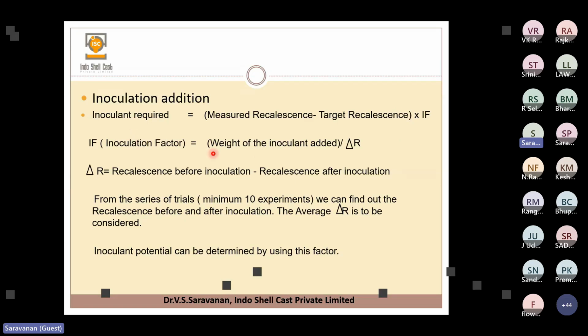So the inoculation factor is the weight of the inoculant added divided by delta R. Delta R is nothing but the recalescence before inoculation and the recalescence after inoculation. For that, we have to take a minimum of 10 to 15 trials at least to fix the inoculation factor. That is very important. A greater number of trials will give a more accurate inoculation factor. So based on that, we can predict.